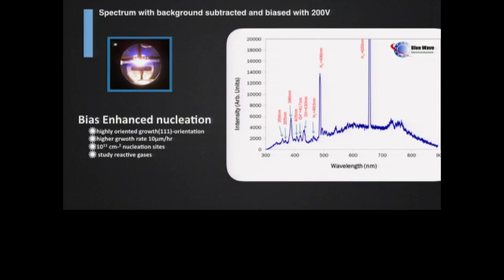And with this bias, by taking a spectrum of the colors of the gas that are created in here and subtracting off the background, you can actually identify the various peaks that are associated with various free radicals that you can monitor during the growth process.